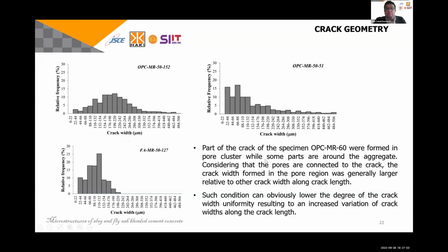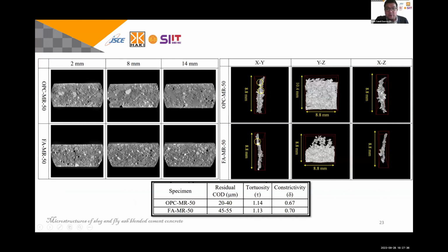So as you can see here, part of the crack in the specimen in OPC were formed in the pore cluster, while some part are around the aggregate. Considering that the pores are connected, the crack width formed in the pore region was generally larger relative to the crack width along the crack length. Such condition can obviously lower the degree of crack width uniformity, resulting in an increase in variation of crack width along the crack length.